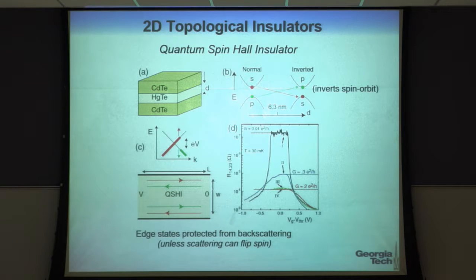On the other edge, it's reversed. So again, if I want to take a spin up electron that's propagating in this direction and backscatter it to go the other way, either I have to flip the spin to get here. I can't do that unless I have magnetic impurities in the system. I need a way to transfer angular momentum. Basically, I need a magnetic impurity to do that scattering. So it doesn't happen in the clean system. In order to backscatter, this one would have to go all the way across here again.